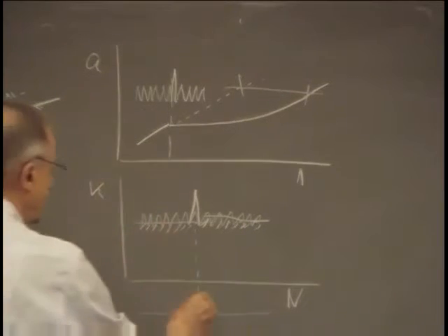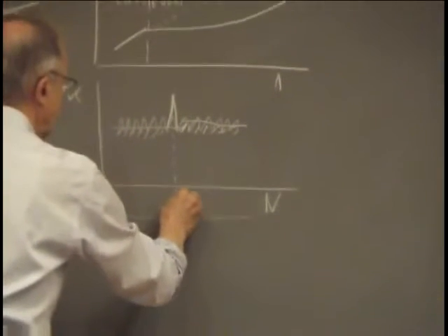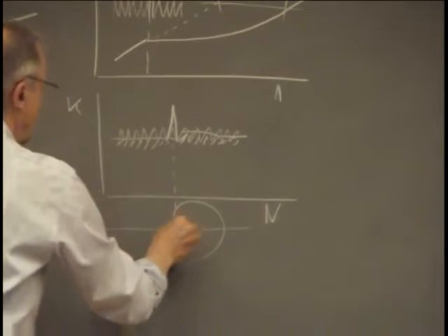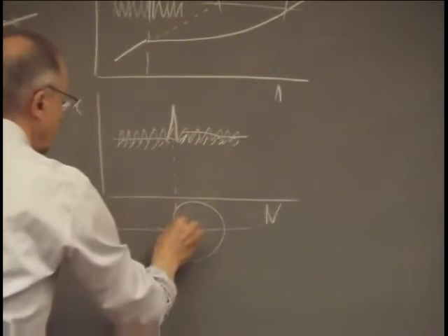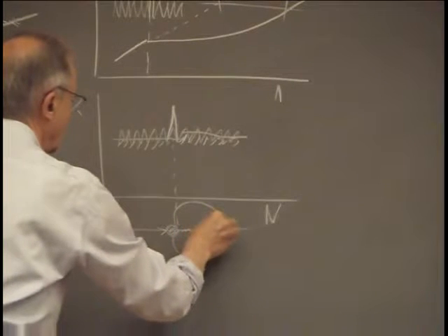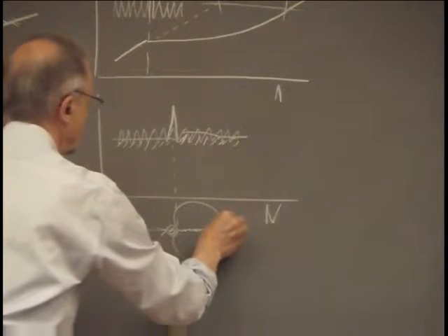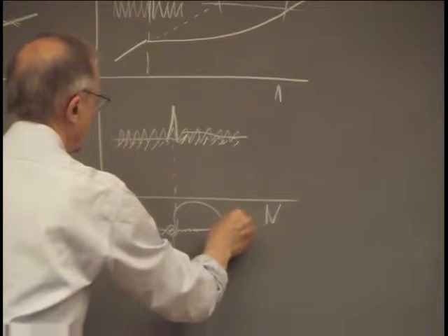And the single peak overload here creates a large plastic zone, and the equilibrium is regained as soon as the crack has left the overload plastic zone and everything is like it was before. So there is a correlation. It is an experimental finding, an experimental correlation.